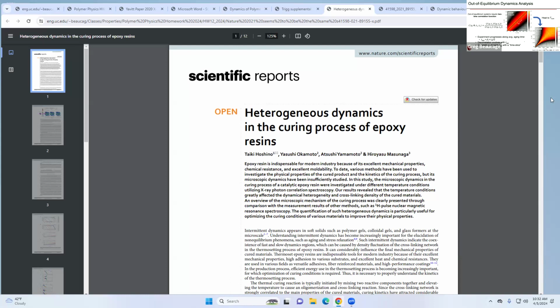Possibly. So if it reconverges, what does that say about the dynamics? Start to speed up again, right? If you have very narrow, thin lines, that means it decorrelates really quickly. And if you have big, kind of chunky, dark domains, that means it decorrelates really slowly, right? So that's the relaxation time we're looking at.